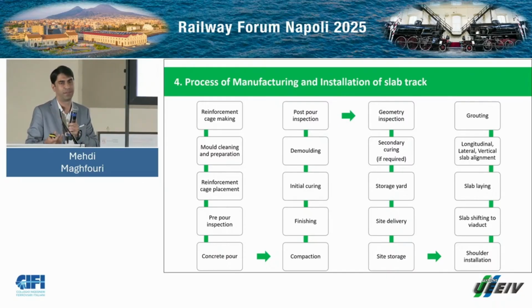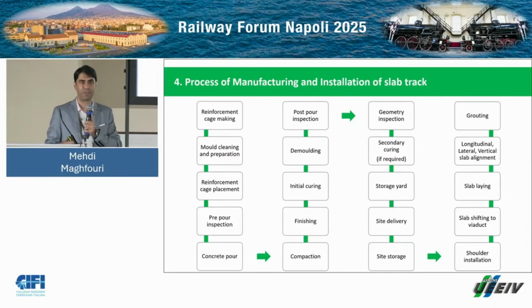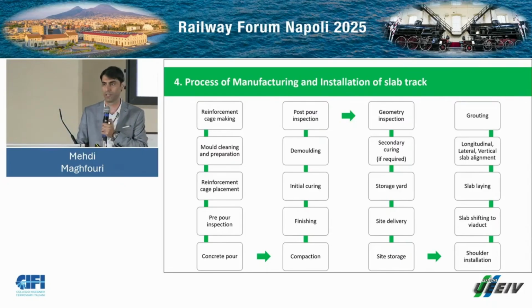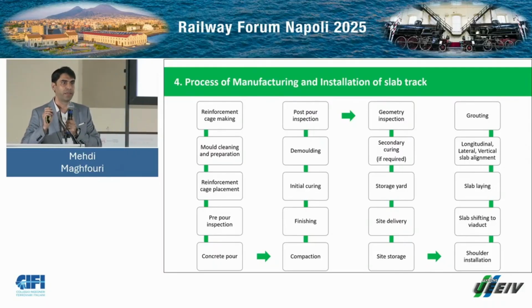That is the reason that Japanese are really particular. But basically, we cannot go up to very high temperature because of the delayed ettringite formation, which can cause serious defects in concrete microstructure.